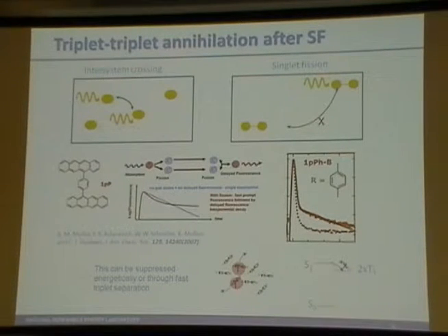And so he interpreted that as the initial decay of the singlet, and this is delayed fluorescence, because it occurs on a much longer time scale, because the triplet lives much longer than the singlet does. And you could kind of get, I would say, a semi-quantitative estimate of the yield in these pentacene dimers. He found it to be a few percent.